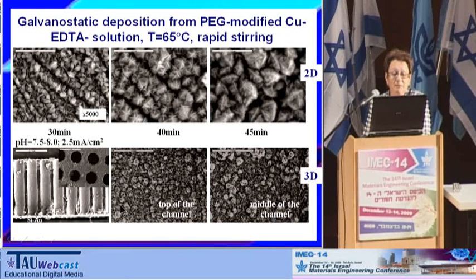The morphology of the semi-three-dimensional copper deposits inside the long and narrow microchannels is very similar to that obtained on the planar substrate. However, the size of the grains in this case didn't exceed 1 micron.